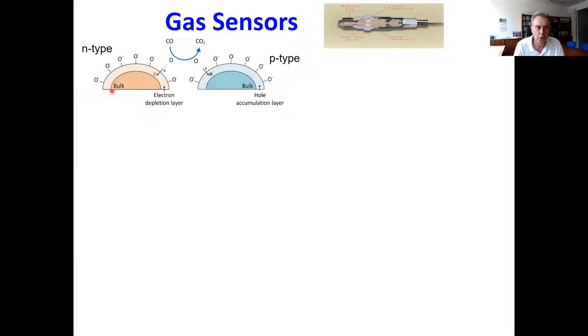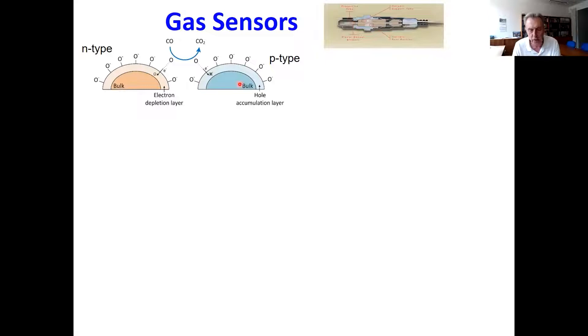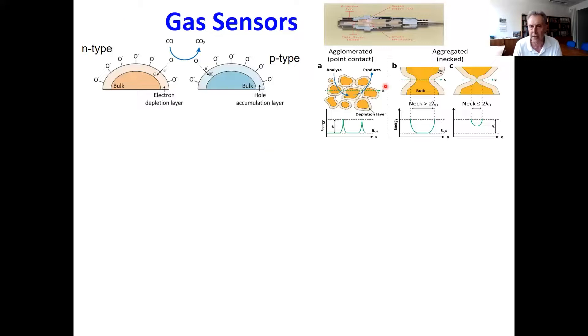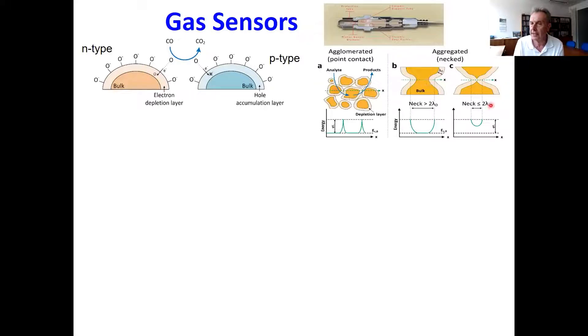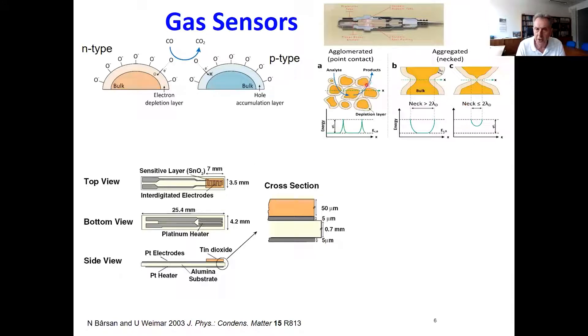How the sensor works: there are two types of semiconductors — n-type and p-type — depending on whether you form an electron depletion layer or a hole accumulation layer around the semiconducting metal oxide. Individual particles are typically a powder that can be agglomerated with point contacts, or aggregated with necks. Making particles at the right conditions with the right structure is essential for sensors, as you will see in upcoming slides.